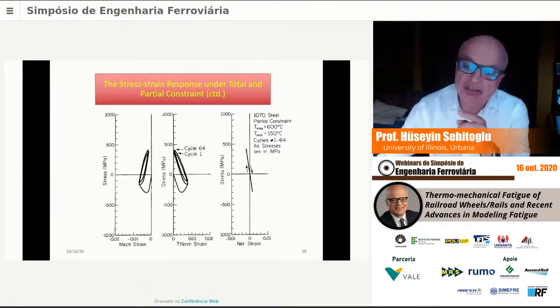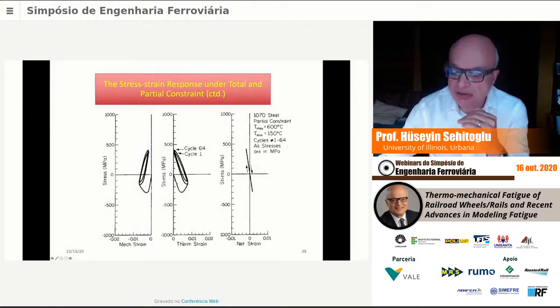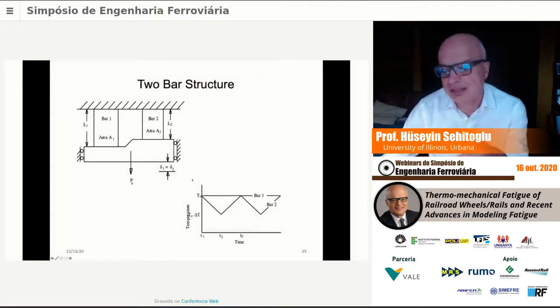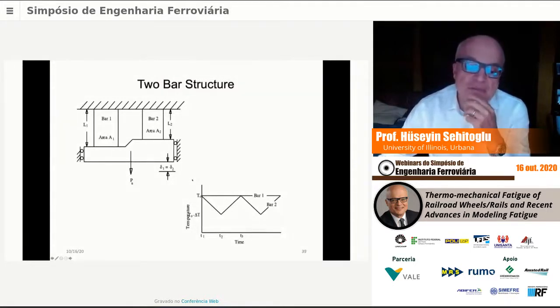I take the same case, 150 to 600, but I allow partial constraint. This is a laboratory experiment where you're allowing some free expansion, which is shown here. As you heat, you're allowing some free expansion, and in that case the mechanical strain is much smaller than the thermal strain. As you cool, it can also contract. So the stress range is much smaller in this case, and the mechanical strain range, which causes the fatigue, not the net strain, is much smaller. Consequently, partial constraint is more desirable.